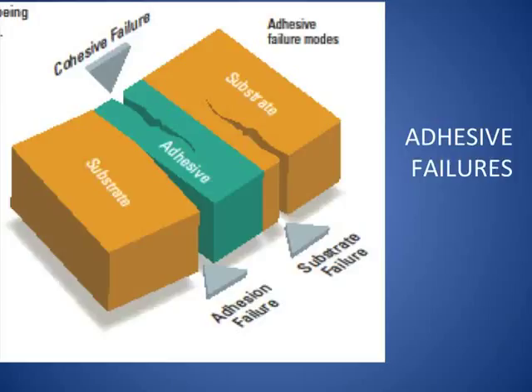Failure in adhesives: you either fail the joint in the adhesive, which is called a cohesive failure, or between the adhesive and the substrate that you're trying to bond together, called an adhesion failure. Or if you have a really strong adhesive and a weak substrate, such as, say, an epoxy and cheap E-glass laminate, it's quite likely you're going to fail the substrate or the underlying material. In steel shipbuilding, which is most commonly the form amongst most of these SNAME get-togethers, we're not usually failing the substrate with adhesives. But I know some of you out there have more of a composites background, so it's sort of a toss-up as to what your adhesive is and what your materials are, as to what's going to fail when you start to pull things apart.